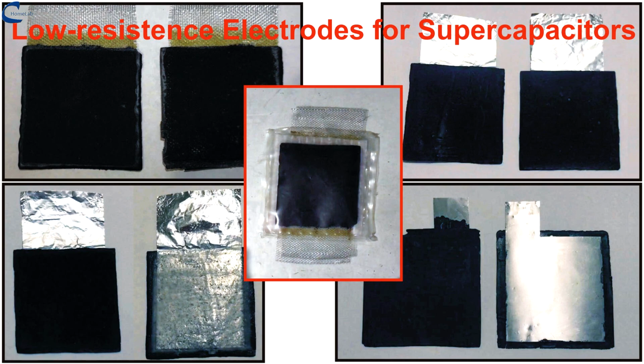But since the electrical resistance of carbon is always higher than that of metals, it is necessary to resort to a low-resistance metal collector. Copper and aluminium are excellent candidates, and when compared on costs, aluminium seems to be the most affordable. Here however, a problem arises, because if we have the two elements carbon and aluminum in contact with each other, and in the presence of an electrolyte, we will have corrosion of the element with lower electronegativity, in this case the aluminum collector, which will slowly turn first into oxide, and then into aluminum hydroxide, in the case of aqueous electrolytes. The consequence will be first an increase in electrical resistance and then the dissolution of the collector.